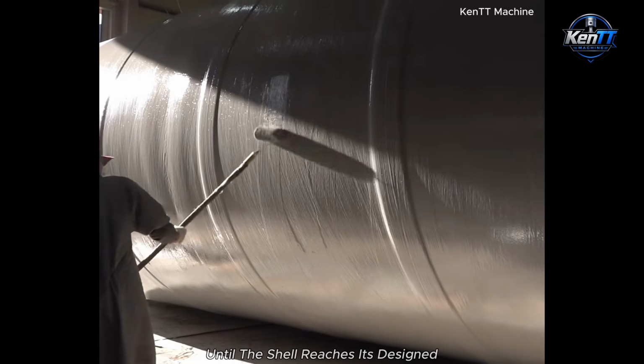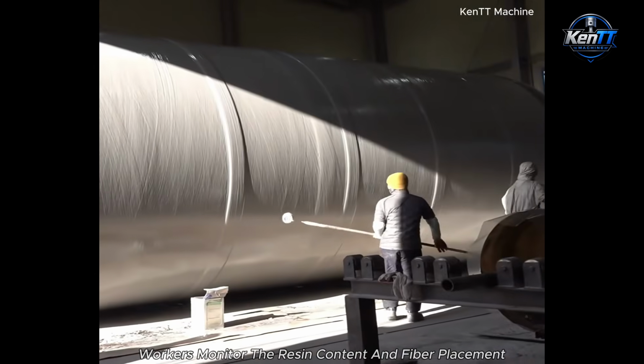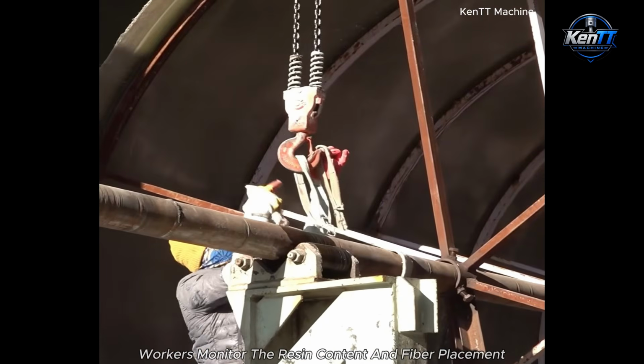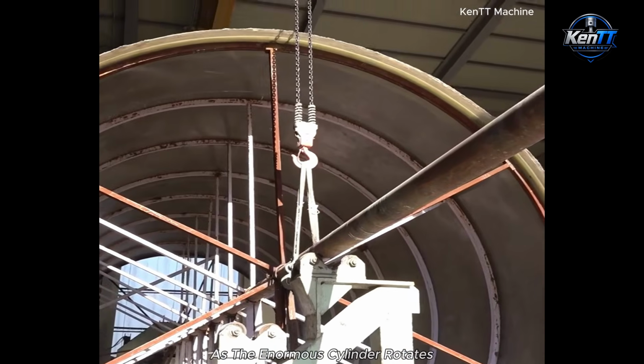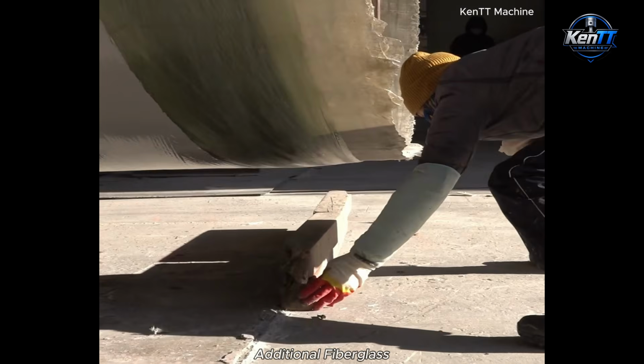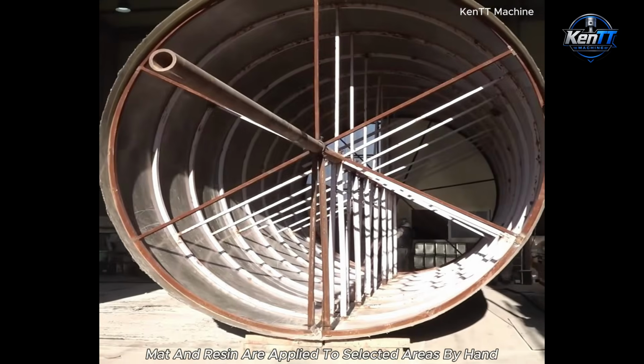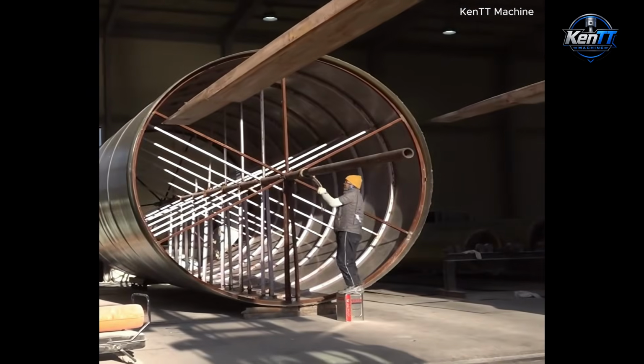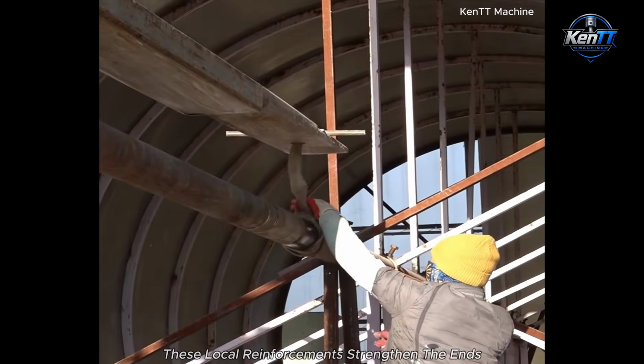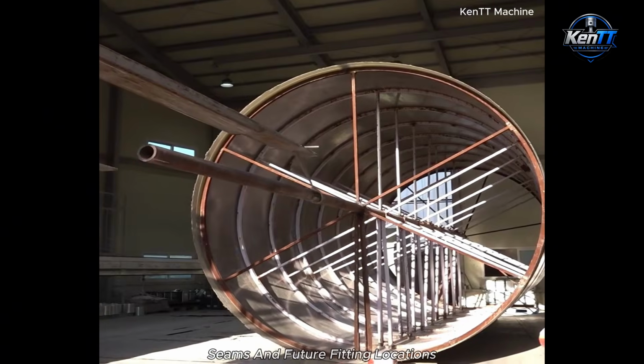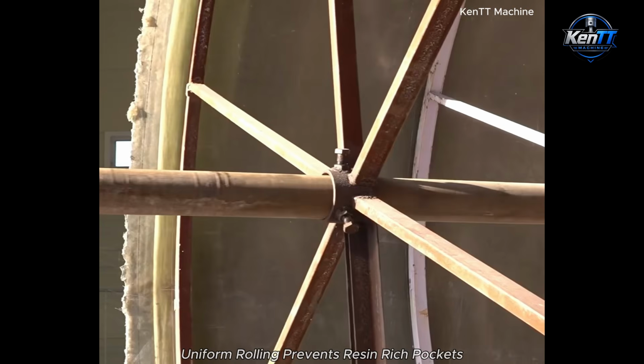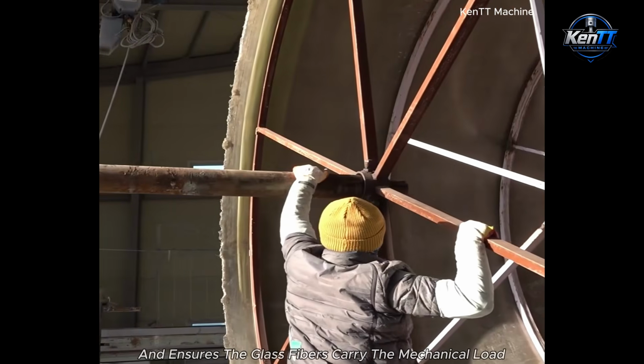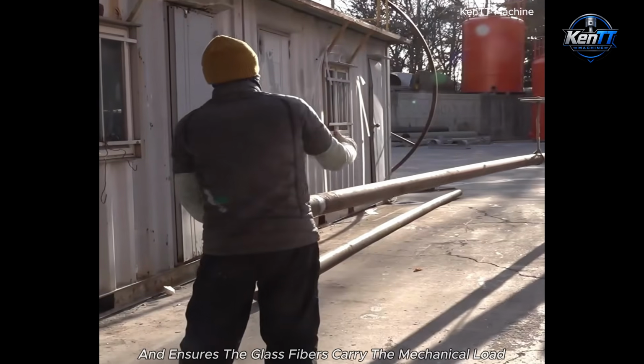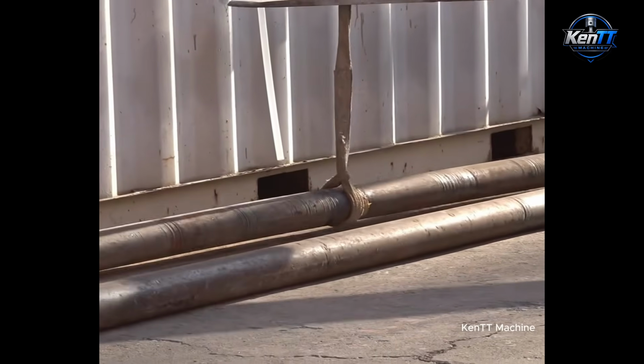Filament winding continues until the shell reaches its designed structural thickness. Workers monitor the resin content and fiber placement as the enormous cylinder rotates. Additional fiberglass mat and resin are applied to selected areas by hand. These local reinforcements strengthen the ends, seams, and future fitting locations. Uniform rolling prevents resin-rich pockets and ensures the glass fibers carry the mechanical load effectively.